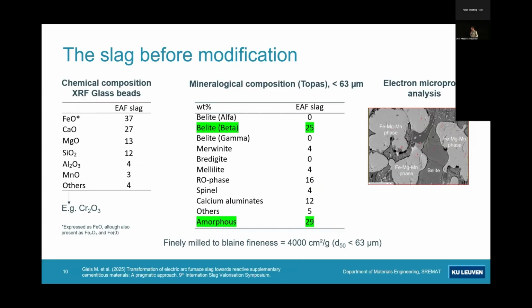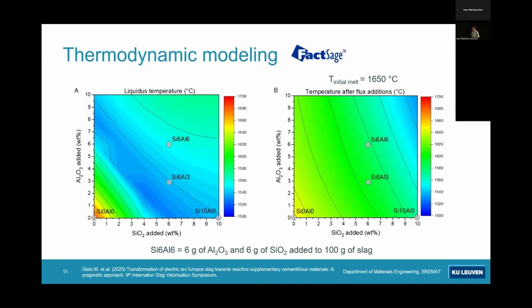So just something about the slag before going into the results. This is, I would say, a typical EAF slag. This is from Nucor, quite iron rich. If you look at the slag as is, it has very low amorphous content. And for the cement people, we would like to see that amorphous content higher, because amorphous most of the time means more reactivity. But of course, there are also some other minerals inside which can be interesting as they have latent hydraulic properties. However, for now, we focused on optimizing the amorphous content.